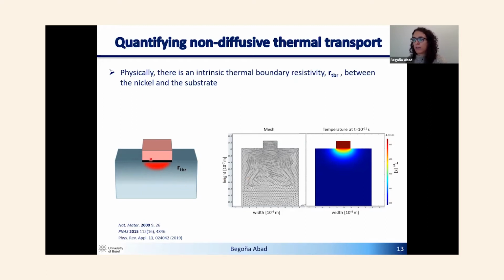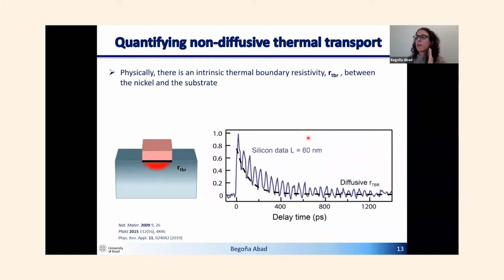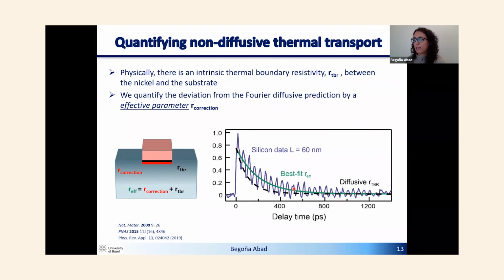So if we use the thermal boundary resistivity intrinsic to these two materials and fit our results for a nanoline that is very small, 60 nanometers, we see that the fitting is not really good. So if we let this thermal boundary resistivity vary, we see that there is actually a change in this parameter, and we need a larger value of this parameter to be able to fit our results. And this correction is what we use to quantify the non-diffusive thermal transport.